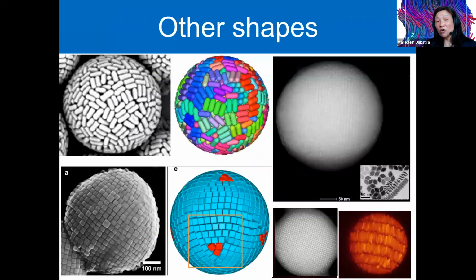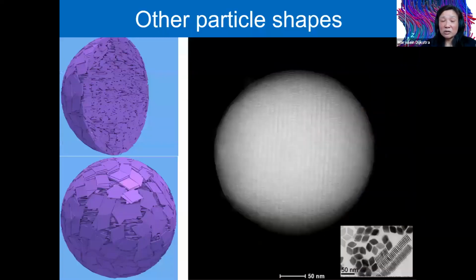One can also look at other shapes, short rods. One can even make smectic layers inside the spherical confinement. One can also look at platelets. These are diamond-shaped platelets. They form nice columns, and so these superparticles are completely filled with these columns of platelet particles, which can also be shown here.